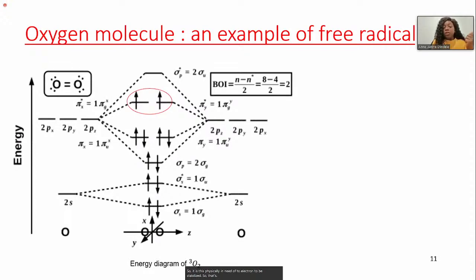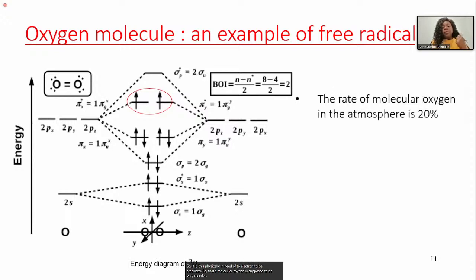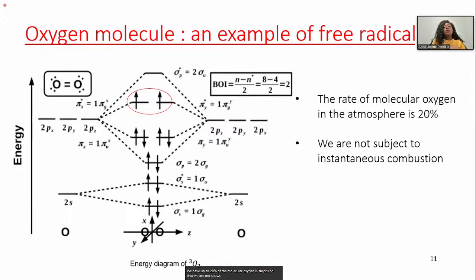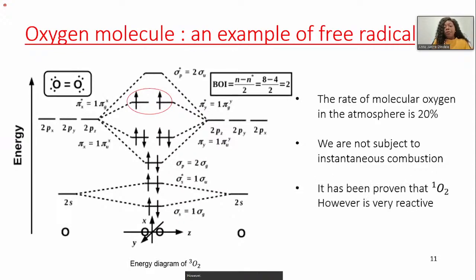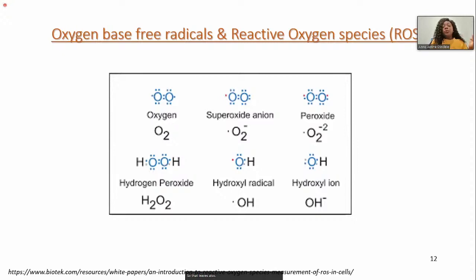So that molecular oxygen is supposed to be very reactive, since in the atmosphere we have up to 20% of molecular oxygen. It's surprising that we are not just subject to instantaneous combustion. That is because it is not really as reactive as it's supposed to be. However, the two first excited states, the singlet states, are proven to be very reactive. So that leads us to a difference between free radical and reactive oxygen species. One molecule can be a free radical and not really be reactive, and another can be even saturated and be very reactive.